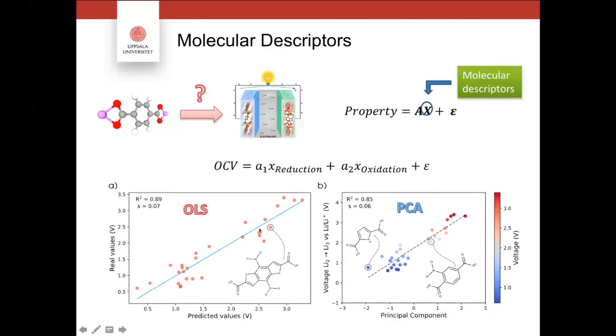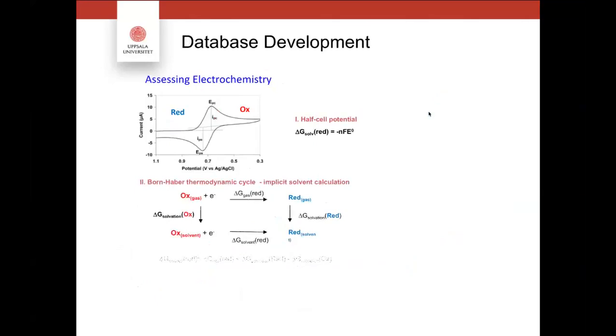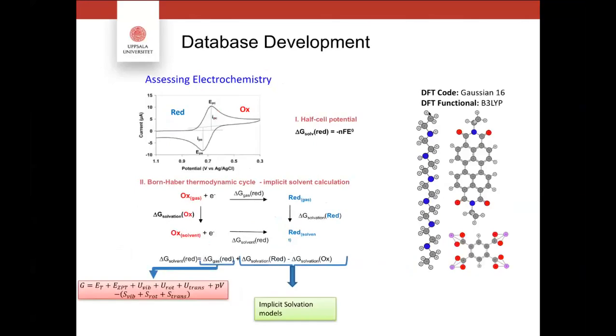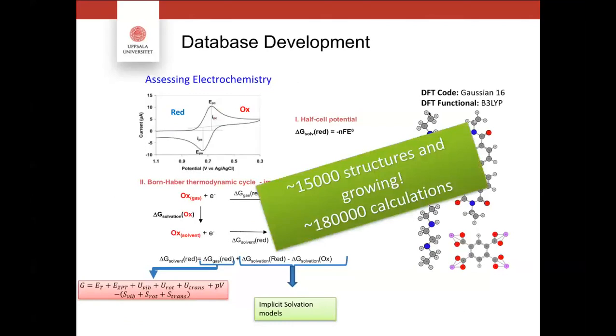And we basically worked both with the ordinary least square regression, but we have also made analysis of this principal component analysis that helped us to have a better clustering of the materials as cathode or anode materials, materials with higher and lower potential. So as soon as we have identified these properties, then we went one step further and developed a way to construct our database for predicting the descriptors. We have now a database that went to something like 15,000 structures, and we have basically started keeping growing this database. It was important because this data was not available in the literature.